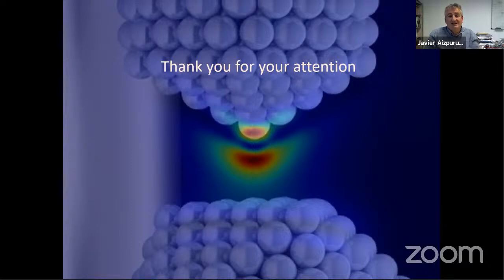And then once the exciton is produced, then this ultra fast process, not femtosecond because it's accelerated, but it can be picosecond or whatever, might be produced, okay? So the excitation dynamical process and the emission decay process can be disentangled perfectly. It's two time scales and it's two different processes. And you can do the same, not with inelastic tunneling current, but with light. You just reduce the bias to a level where the current cannot excite the exciton, but you come with light and you excite the exciton, and again, you have fluorescence. And again, you can disentangle both processes, the excitation and the emission, even with light, light in, light out. This is standardly done in photonics.